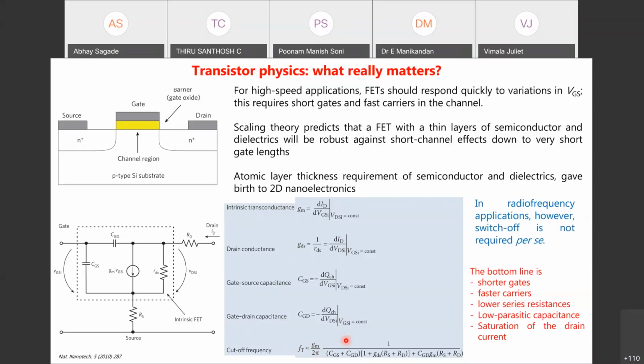What is important to notice here for RF transistors is that there is no off state required. Transistors are well known to be used as an on-off switch, where the off state is important with very low current. But for RF applications, a state with low current is not required. The bottom line is you have to have shorter gates, fast moving charge carriers, low series resistance, and low parasitic capacitance. Importantly, you have to have saturation in the output current. These are the parameters which need to be watched out for when you are going to fabricate your device.